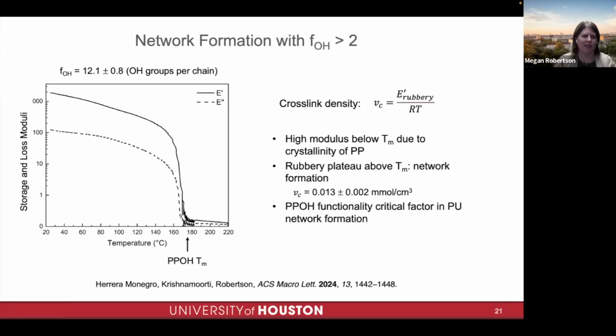And what you can see here, we're looking at a mechanical analysis. This is a dynamic mechanical analysis. So we have the storage and the loss moduli as a function of temperature. At low temperature, the modulus is quite high. Sorry, this is cut off, but there should be an 1,000 there. But this is quite high.